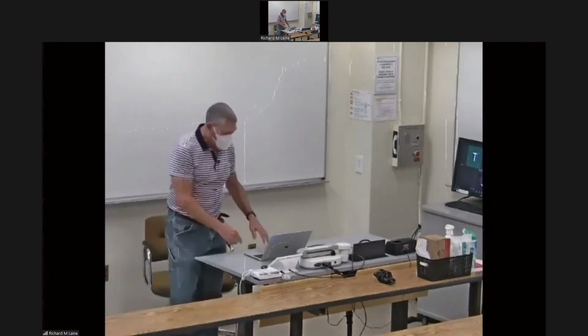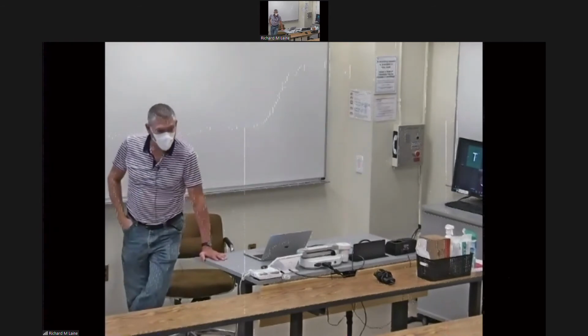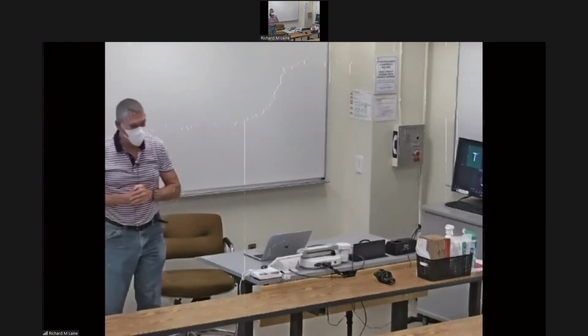So let's start by examining what it is we see in organic electrolytes and how they differ from water. So the dielectric constant of water is 80. Some of the liquid electrolytes, and we will spend some time with them, have dielectric constants of 30 and 40. So in a concentrated solution with ethylene carbonate, or this is actually propylene carbonate, but if it were, then lithium is partially solvated, but now the tetrafluoroborate anion is within a strong interacting distance with the lithium. Even though the tetrafluoroborate is supposedly a diffuse anion, okay? So it shouldn't be strongly attracted, and that's our basis here.